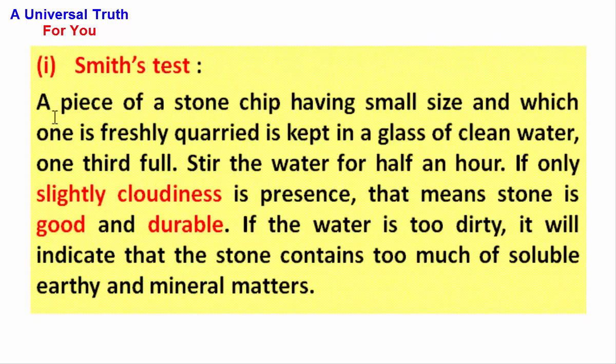Smith's test: a piece of a stone chip of small size which is freshly quarried is kept in a glass of clean water, one third full. Stir the water for half an hour. If only slight cloudiness is present, that means the stone is good and durable. If the water is too dirty, it indicates that the stone contains too much soluble earthy and mineral matters.